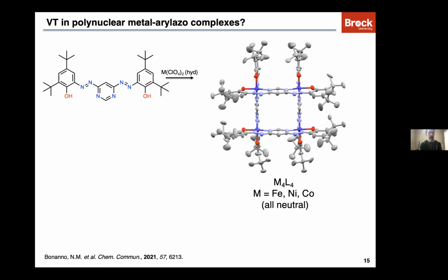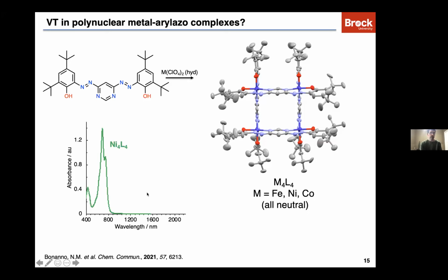Now, a more clear example of valence tautomerism in aryl azo complexes we've recently published in ChemComm is with this ditopic aryl azo ligand. So we've produced this. I won't go through the synthetic details, but it's only a couple of steps to make this. And if you coordinate this ligand to metal perchlorates, you get these very strictly 2x2 grid type complexes. We've made iron, nickel, and cobalt versions of this complex, and in all cases, these are neutral complexes, no counter anions. Now, for the nickel and iron complexes, we see very typical metal aryl azo type behavior. So you have very intense visible absorption bands, suggesting that we have a coordinated ligand dianion just by simple deprotonation of those two phenols.